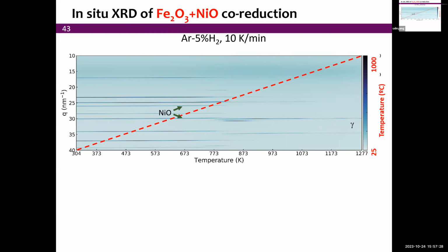Now, if we add iron oxide to nickel oxide, so that's kind of a prototypical steel, here's what we have. We, of course, have the nickel oxide, so the same story I told you already. We have the iron oxide Fe2O3, and then we start a cascade of transformation from Fe2O3 to Fe3O4 to FeO, and eventually to alpha iron. So iron oxide has those multiple suboxides. And so we see clearly as a function of temperature that we go through what the phase diagram would in fact predict.